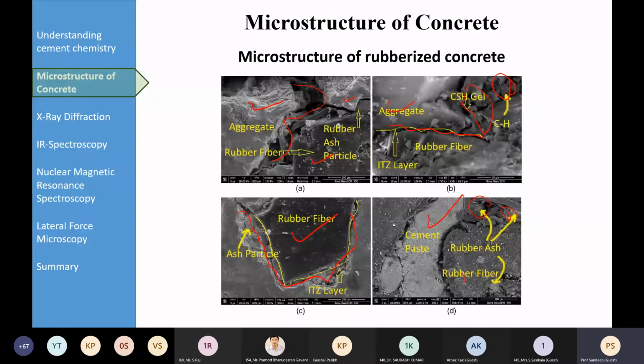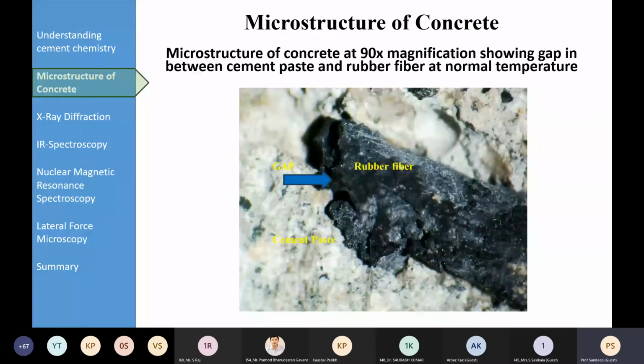You can even see the effect of temperature. You don't need to go even for a scanning electron microscope because that's a costly equipment, which costs more than 1 crore rupees. But you can use normal optical microscopes also, which cost less. So here, through the optical microscope, the images were taken and we tried to see the effect of temperature on this rubberized concrete. Here you can see it's just a 90x magnification level. Even at 90x, through a normal optical microscope, which is available in most laboratories, you can easily see this gap between cement paste and rubber fiber, very clearly visible. So you need not always go for that high level.